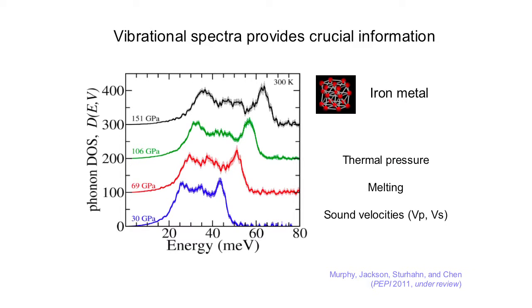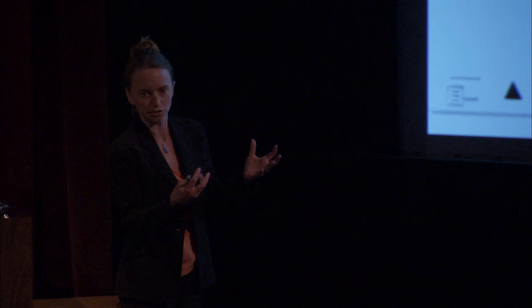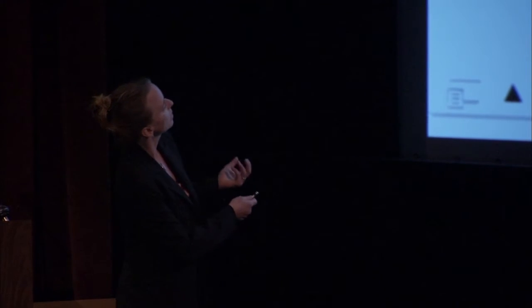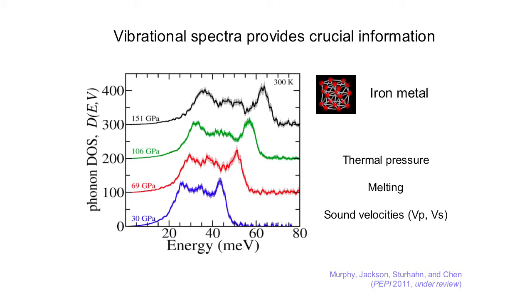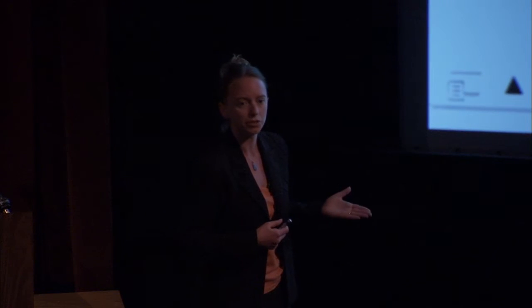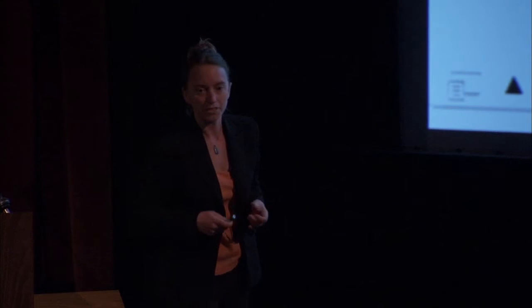And so we've taken a densely packed iron metal in the hexagonally close packing arrangement, and we've measured the vibrational properties. So all of these modes here characterize the vibrational states of this iron metal that's compressed all the way to 151 GPa. And this is now into the core pressure. So we're at 1.5 megabars. The core-mantle boundary is 1.4 megabars. And in these measurements, simply by probing all the vibrational states, we obtain a thermal pressure, which will help us with the understanding of how the material melts. And we can also determine the sound velocities.